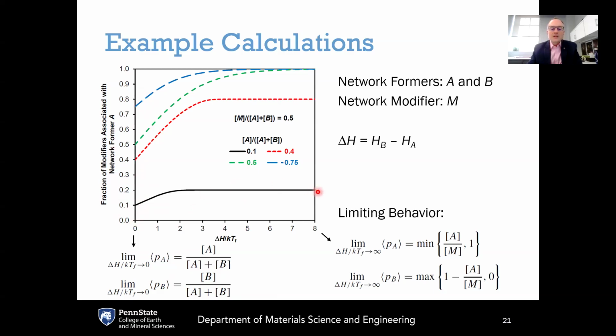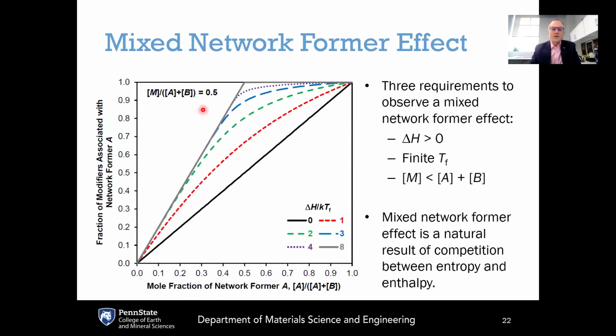If you take the opposite side, so going to a limit of large delta H over kTF, this would be the energetic limit. So you'd have kind of the most chemical ordering in the glass would occur in this limit, because here, this is where you have a large energy difference or large enthalpy difference between modifiers associating with network former A or B, and then everything in between. So it's entirely governed by entropy on the left-hand side, entirely governed by enthalpy on the right-hand side, and then trade-offs between the two in the middle.